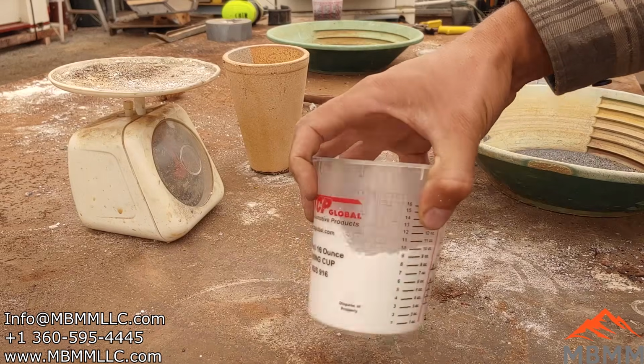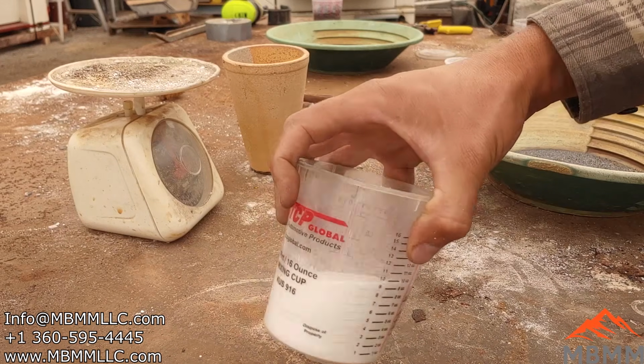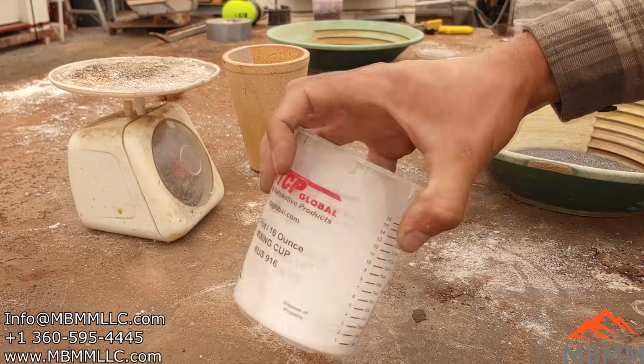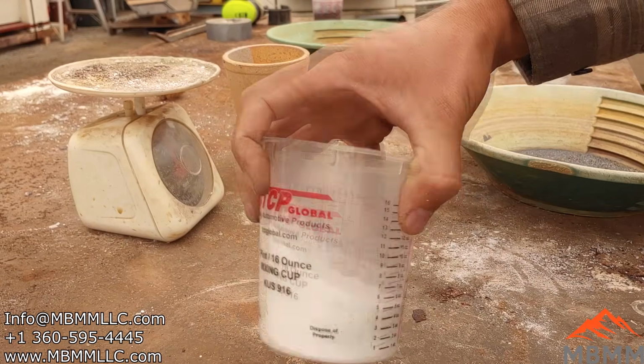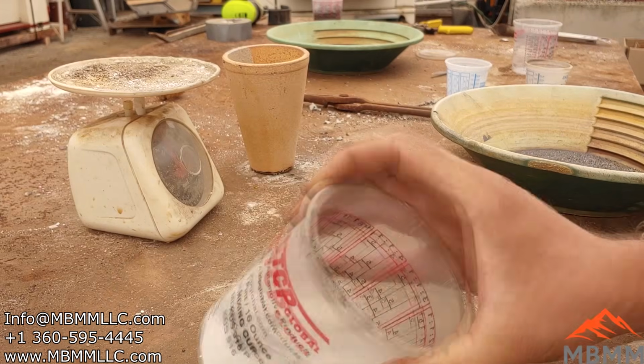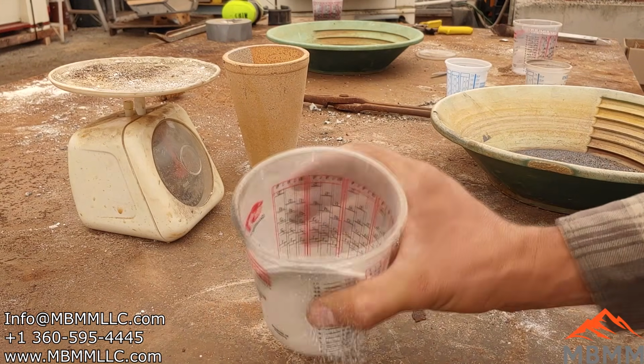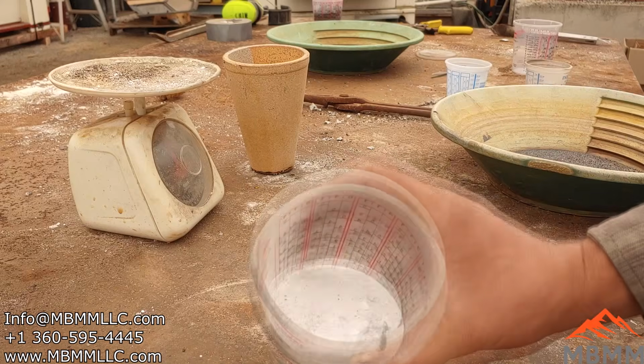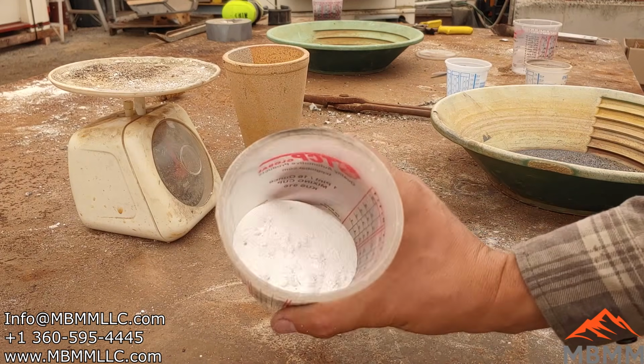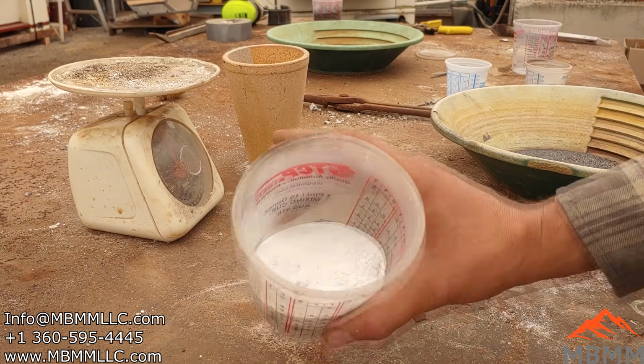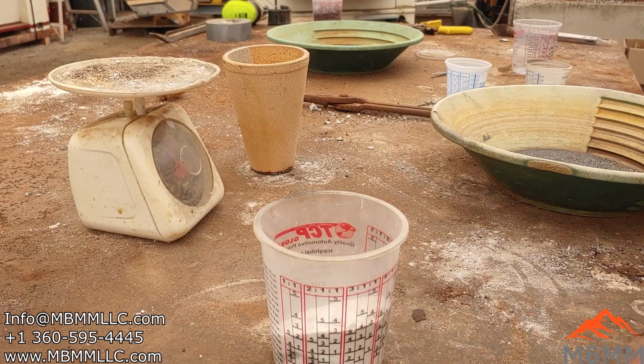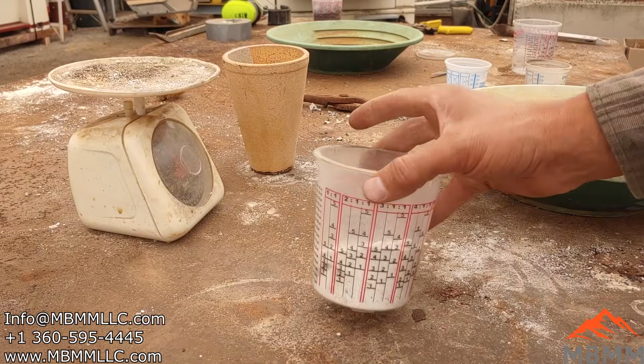And the lead button, we will then cupel away, oxidize the lead, which I'll talk about here after we're done smelting this first one. We'll oxidize the lead and end up with our silver button in our cupel. So let me get this mixed up real good. We'll add it to our crucible over here. I'll throw a couple nails in there, maybe an iron rod, and then we'll put it in the furnace.